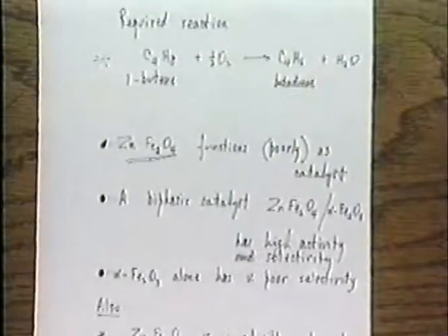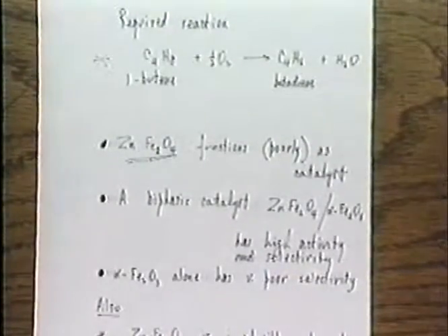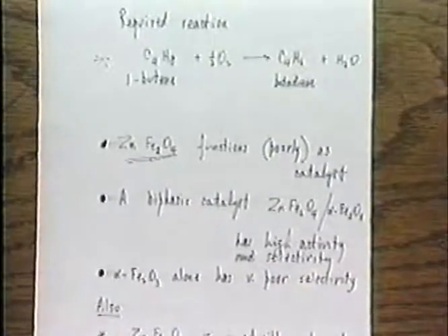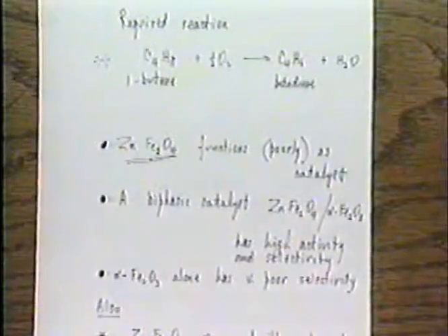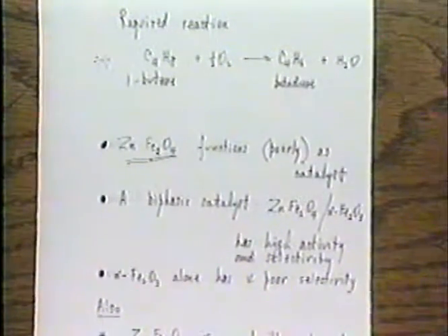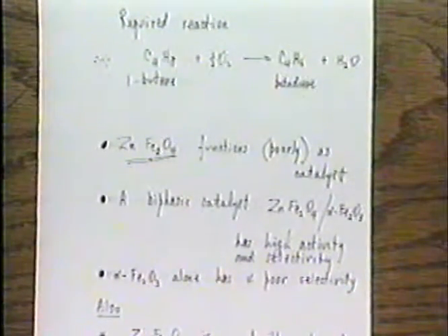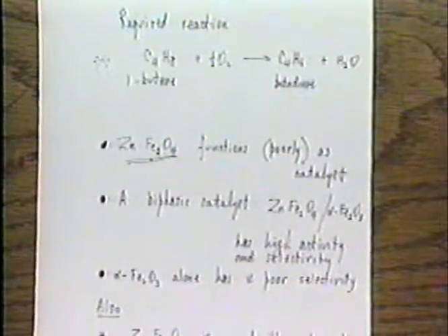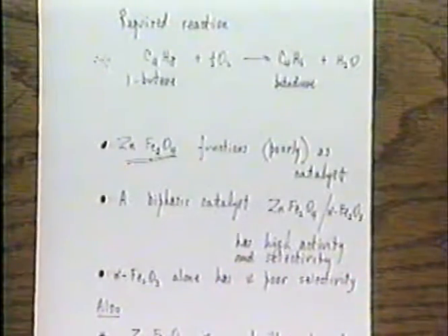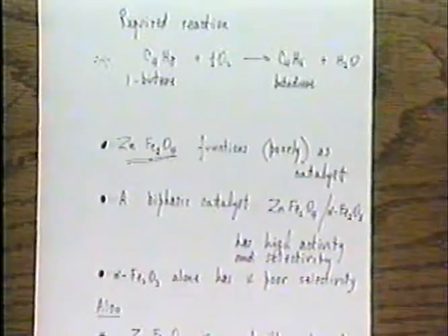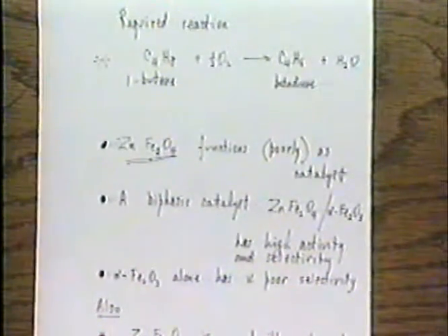It becomes very difficult to find sites upon which oxygen can be adsorbed by electron transfer, because you would expect the electron transfer process for the adsorption of oxygen as an ion of some description to require electrons to be transferred out of metallic ions which are situated in the surface of the catalyst, and the electrons are transferred to the oxygen. There must be some degree of reducibility of the iron in zinc ferrite to make this possible, but it appears to be a very poor function.